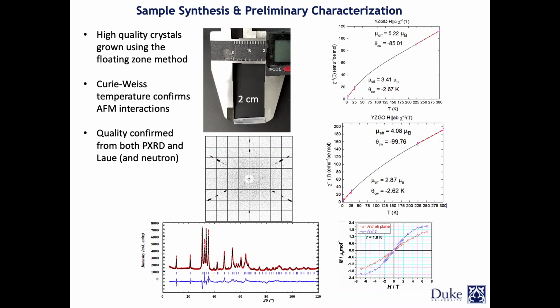If it, for example, has a preferred orientation, a preferred axis, or a preferred plane, then depending on the direction of the field, it is going to require more or less energy. Here you can see that this is the field and this is the magnetic moment. You can see that when H is parallel to the ab plane, less energy is required while the magnetic moment is lower.